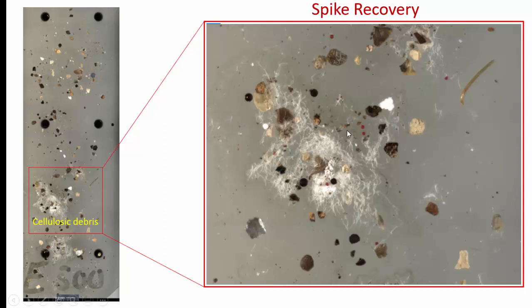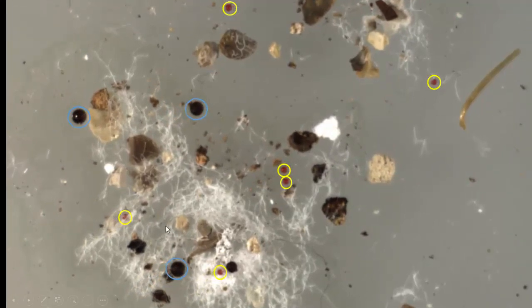So this was the samples that we analyzed using the Loader protocol with the enzymatic buffers. And you'll see there is some cellulosic debris still present in the sample, but it's probably 99% removed from what it was in the original wastewater sample. You see these large particles. These were obviously an influent sample, and we spiked them with 2 different types of polymers. And I've highlighted those here. The red polyethylene polymers, these were 70 to 120 microns, and the larger particles were another polypropylene that was in the 200 micron range in size.